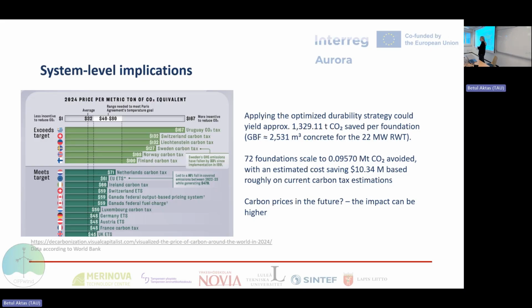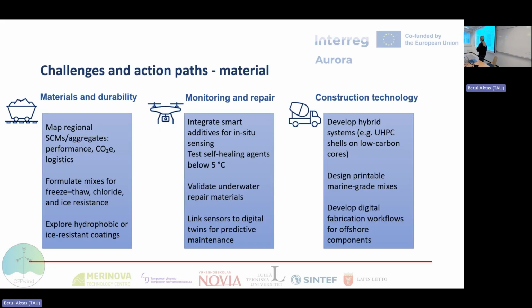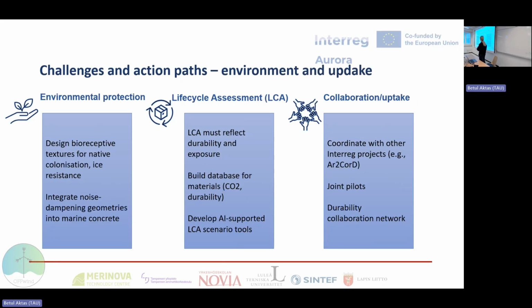With the increasing carbon prices in the future, we can actually predict that the impact from the CO2 decrease by the low carbon concrete can be even higher. So it can have a positive effect on the whole acceptance of those kind of structures. So we also established some additional challenges and potentially interesting topics to study. I will refer you to our report to not waste too much time.